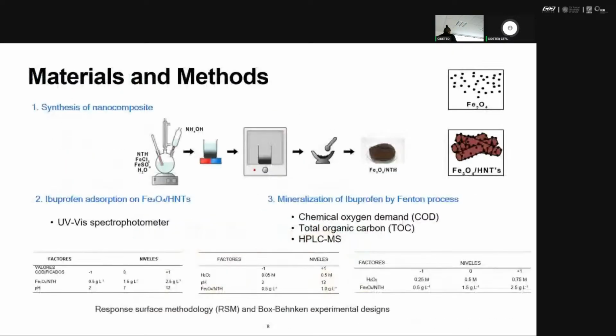Okay, the materials and method. This work consists of three parts. One is the synthesis of the composite, for which I use a co-precipitation method using iron oxide in the presence of a basic medium. It is easy to synthesize magnetite. So I synthesize magnetite, and I synthesize the magnetite supported on the halloysite.